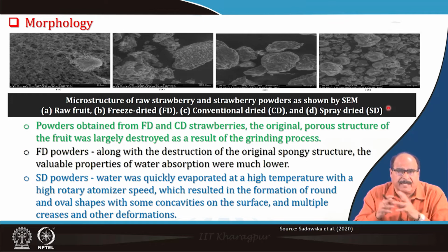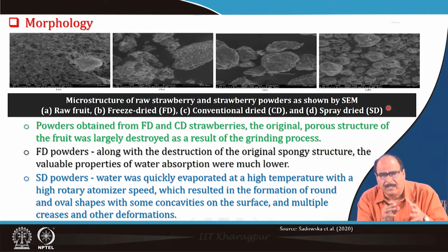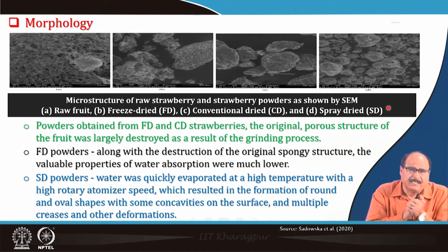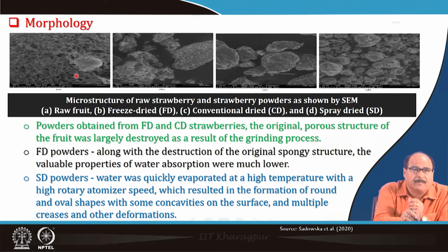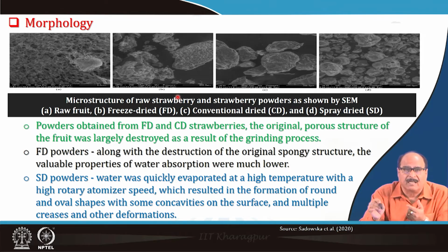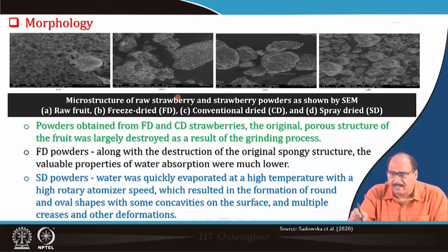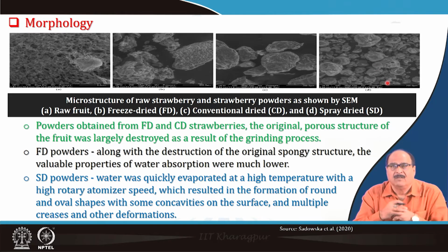Then the morphology. When we dry and prepare this powder, depending upon the method of preparation, the morphology of the material may get changed. You can see here there are 4 pictures. Number 1A is the microstructure of a raw strawberry fruit, and the second one, B, is the microstructure as found from the scanning electron microscope, that of freeze dried strawberry powder. C is the conventionally dried, and finally the last one, D, is the spray dried strawberry powder. And you can see the difference in the structure.